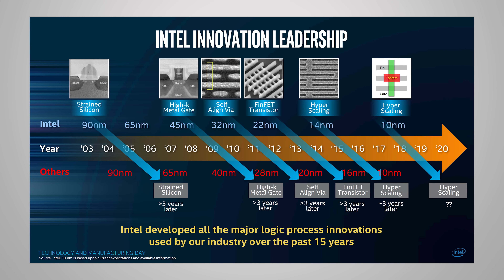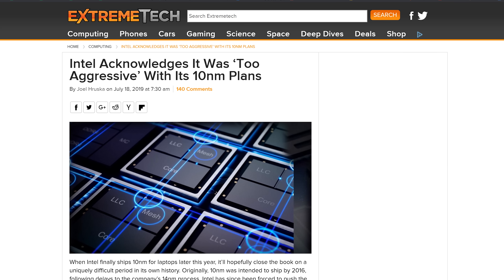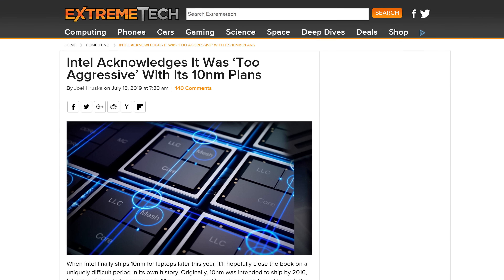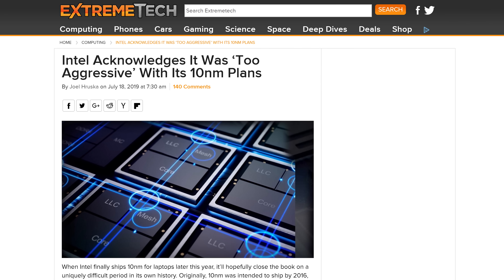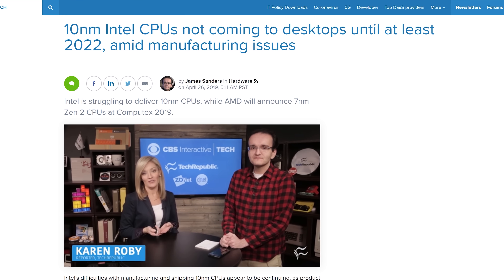In addition to density, chip makers are using other techniques like improved materials to boost performance. This can include squeezing the crystal structure of the channel to make electrons go through faster, low-resistance traces between transistors, and gate materials with a high dielectric constant for better control of electron flow. Intel's well-publicized difficulties with their 10 nanometer process were due in large part to them trying to over-scale — packing more than double the number of transistors into the same space — which required many new technologies all at once and caused delays and manufacturing problems.